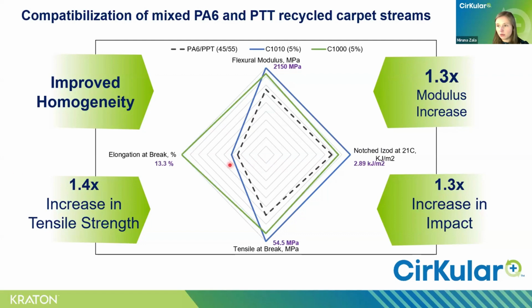And then in green is when we add C1000 at 5% to that recycled blend. So to summarize again, we do see a significant improvement in properties. So 1.4 times increase in tensile strength, a 1.3 times increase in flexural modulus, and a 1.3 times improvement in impact resistance, and overall improved homogeneity of the blend.